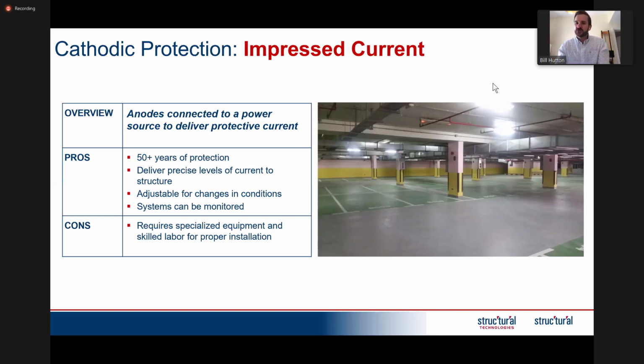Other systems which can be installed are impressed current systems. So there's lots of different anodes out there. One of the most common types would be a mixed metal oxide coated titanium, which could be installed as a ribbon mesh, installed in saw cuts or slots cut into concrete cover, or it could be discrete anodes installed in drilled holes, or it could be an expanded mesh, looks a bit like a chicken wire, installed across the entire surface, encapsulated in a cementitious overlay. So generally, if you're looking to protect large areas, especially horizontal slabs, driveways, then ICCP is a very economical way to provide up to 50 years of corrosion control.